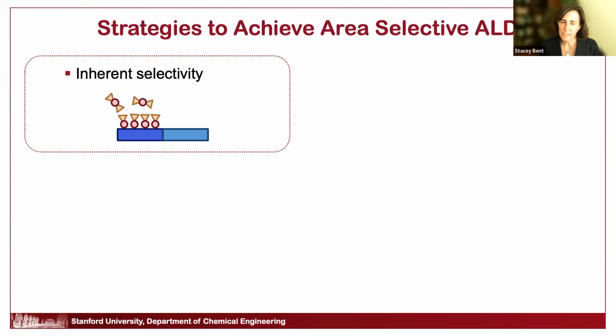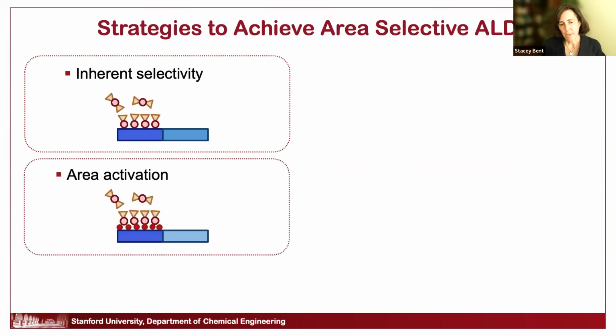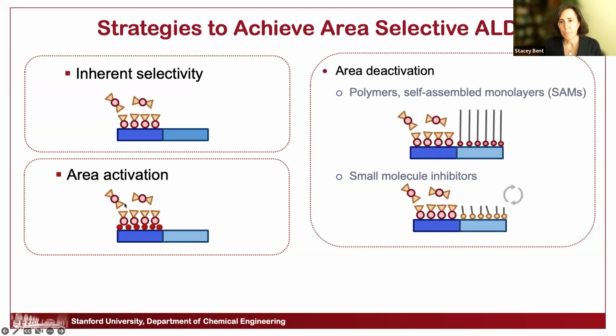Some ALD processes exhibit inherent selectivity. They naturally will go down preferentially on one material over another, but those examples are not very prevalent. There are some cases where one can activate one of the materials over another, so you get preferential growth on the desired region. But by far the most common approach is to deactivate and use an inhibitor molecule, some organic molecule shown here with these circles and tails on them, that go down preferentially on the non-growth region so that when you do deposition by ALD, it goes down on the non-blocked regions.